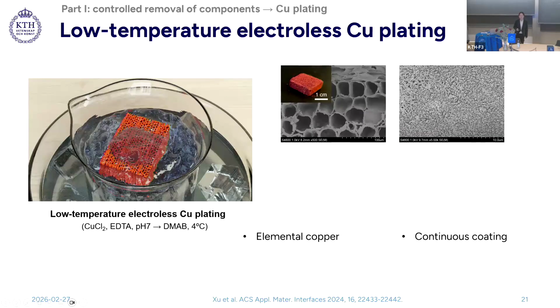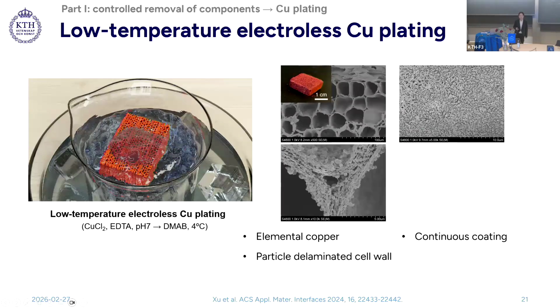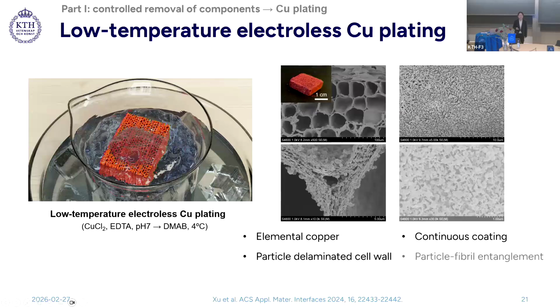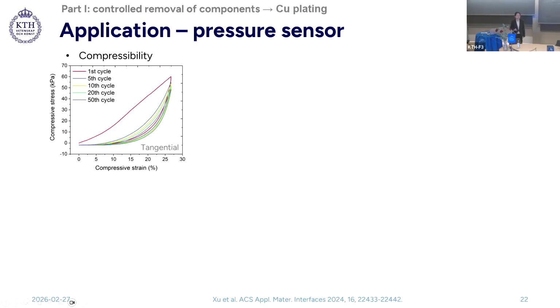In addition to the continuous coating on the surface of cell wall, a multi-layered cell wall structure embedded with copper particles was created. Besides, extensive particle fibril entanglements can be observed on the cell wall, showing the effect of deep metallization. Due to the multi-layered cell wall structure and disrupted cell wall integrity, the obtained composite demonstrates compressibility along tangential direction. The continuous coating also provides good electrical connectivity.